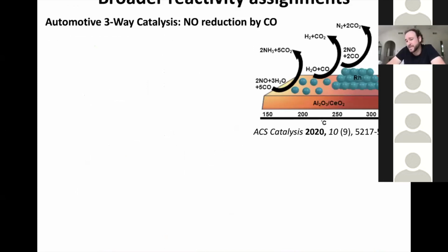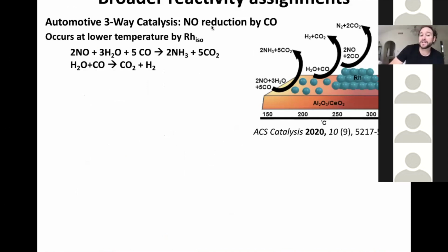So this case I showed you was for CO2 reduction. We've done this many times recently for other chemistries using an almost identical approach. So in another case, we were looking at NO reduction by CO, which is how you reduce NOx in a three-way catalyst, in a gasoline burning engine. One thing that we found here, which was interesting and surprising, is that single atoms in your catalytic converter are actually responsible for ammonia production.